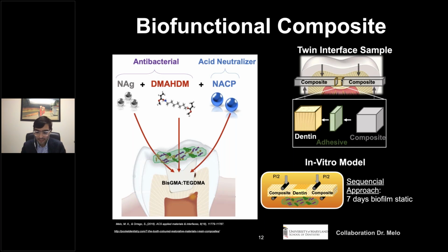And then we added the adhesive layer exactly the same way we do it in clinic. And then we added the composite, which will actually replicate exactly what we see in clinic. So this is defined as the twin interface: we have the dentin block, then the composite and the adhesive.